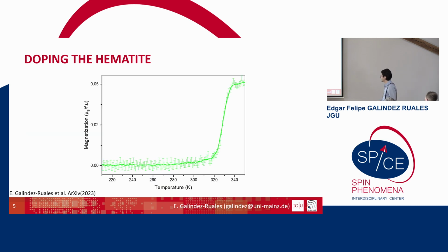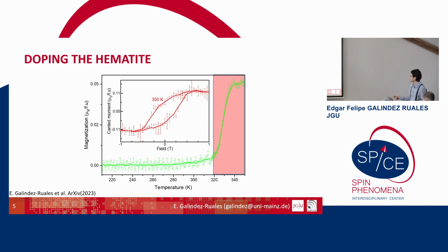Then we measure the magnetization as a function of the temperature, and we measure some field dependence at the basal phase and the easy axis phase. We define the Morin transition when there is no magnetic moment, and if we measure at high temperature, we have a hysteresis loop that corresponds to the bulk value. This is important because we are not increasing the magnetic moment when increasing the doping. That's something that can happen, and when you increase the magnetic moment of your sample while doping, you will have a contribution of the normal Hall effect.